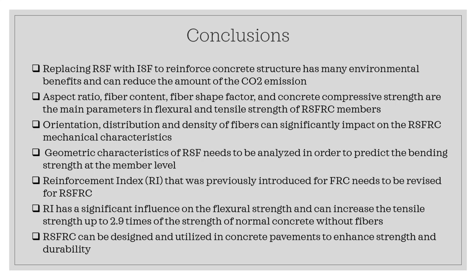And the reinforcement index that was previously introduced for fiber reinforced concrete needs to be revised for recycled steel fiber reinforced concrete. So we incorporated the shape factor, but of course the weight of each needs to be included in terms of how much effect each one has on increasing the load-bearing capacity of a member, or the tensile strength of a member that's subjected to flexure or tension. Reinforcement index has a significant influence on flexural strength and can increase the tensile strength up to 2.9 times the strength of normal concrete without fibers. And the other thing is, recycled steel fiber reinforced concrete can be designed and utilized in concrete pavement to enhance the strength and durability.